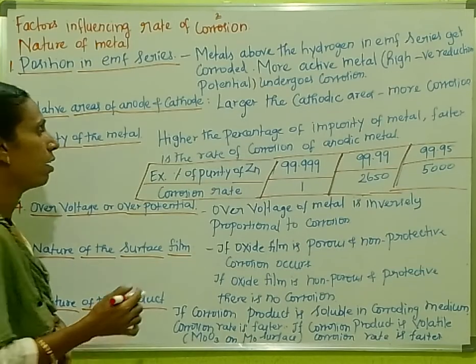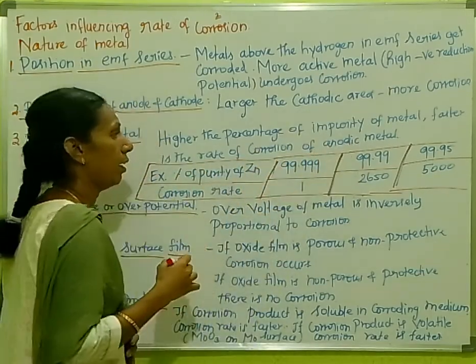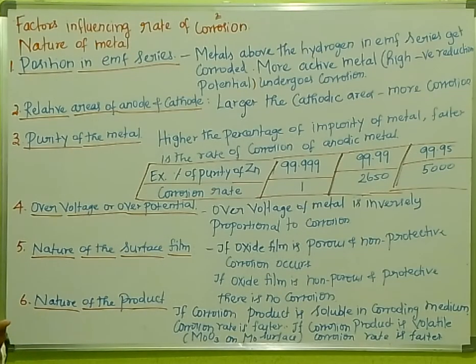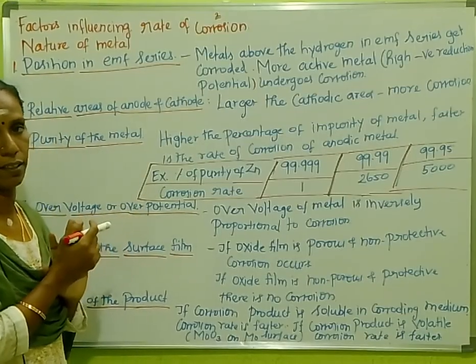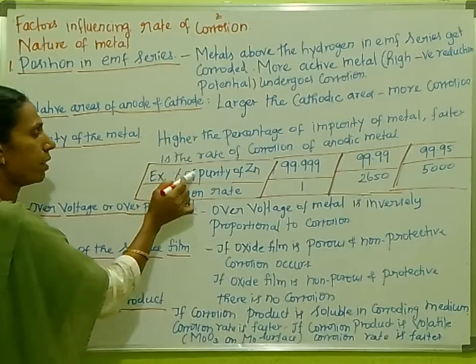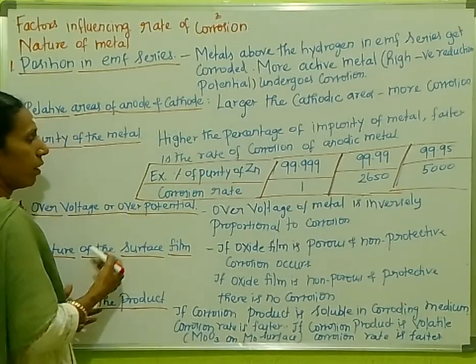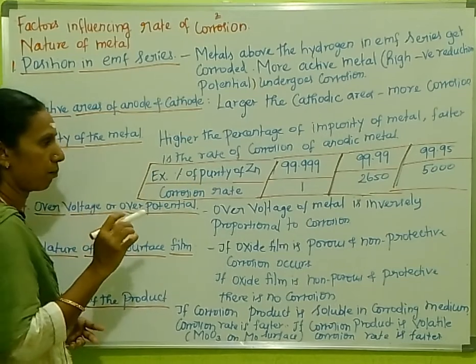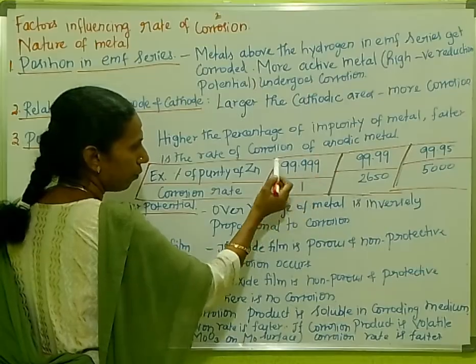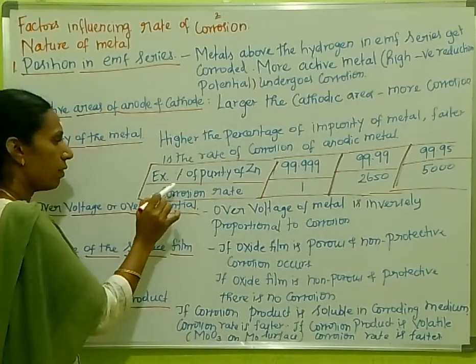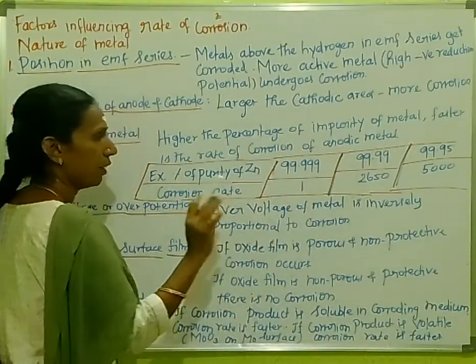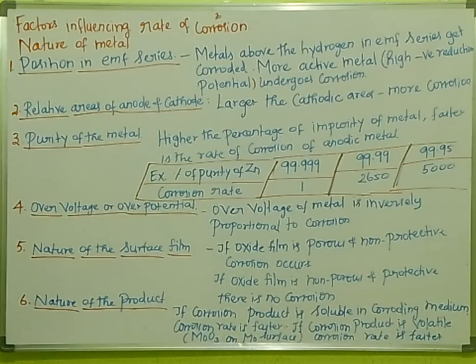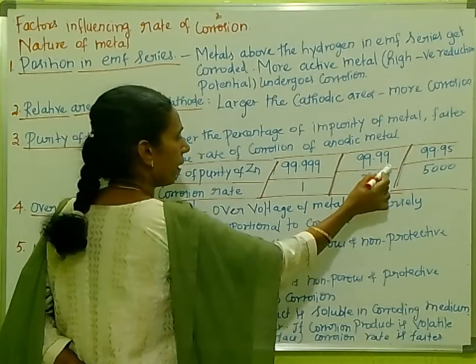For example, consider the purity of zinc. If zinc has a purity of 99.999%, the corrosion rate is 1. If zinc has a purity of 99.95%, the corrosion rate increases to 5000. So, lower purity leads to a dramatically higher corrosion rate.